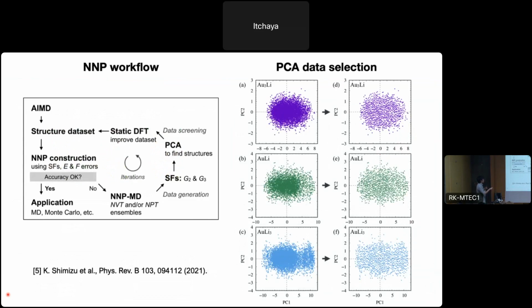The main point is we did a lot of molecular dynamics simulations, but using principal component analysis based on symmetry functions, which represent the local atomic environment, we extracted only the important dataset. This is an example, a PCA plot, where one point corresponds to one structure. We have many data points, but as you can see, many are located at the same point, so those can be eliminated from the dataset. After eliminating the unnecessary data, we get the PCA plot like at the right-hand side. Using this technique, we prepared a 40,000 dataset and trained the neural network potential.